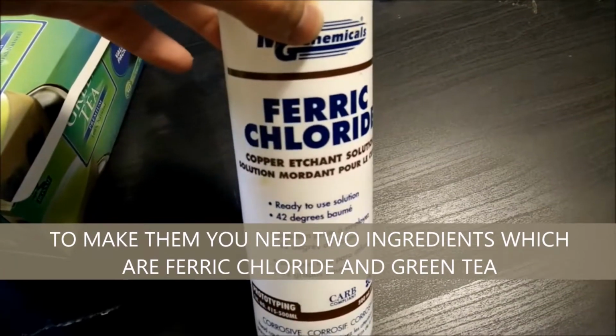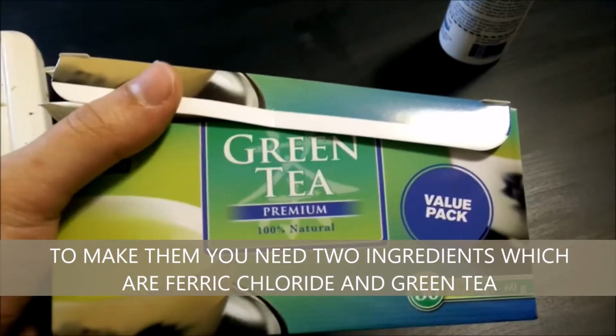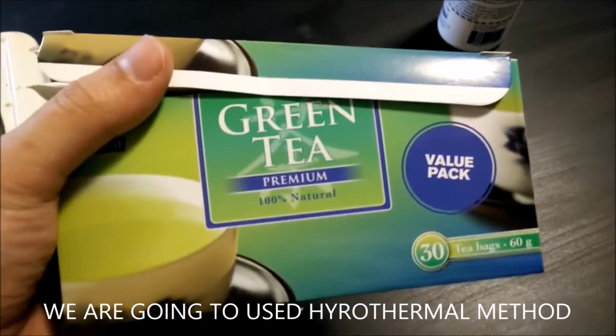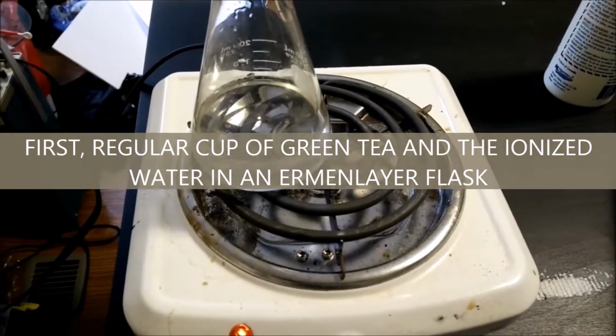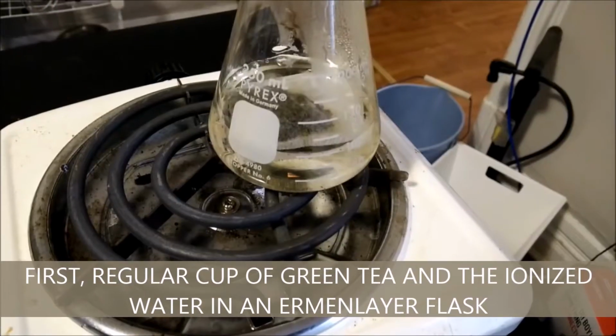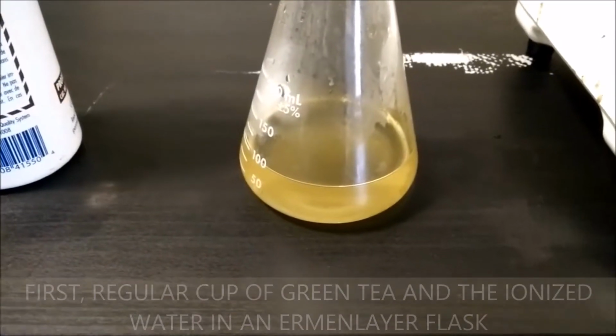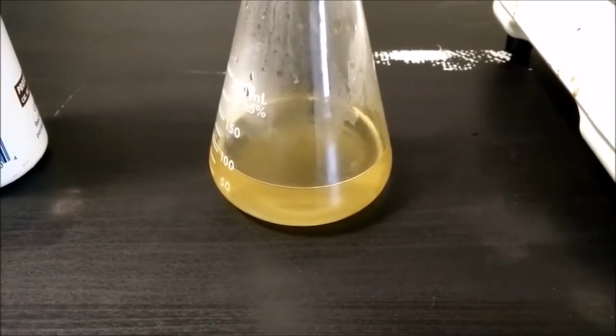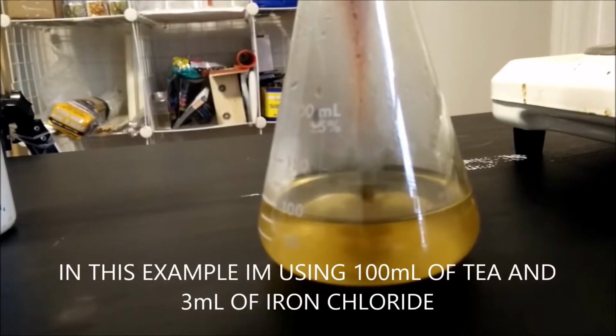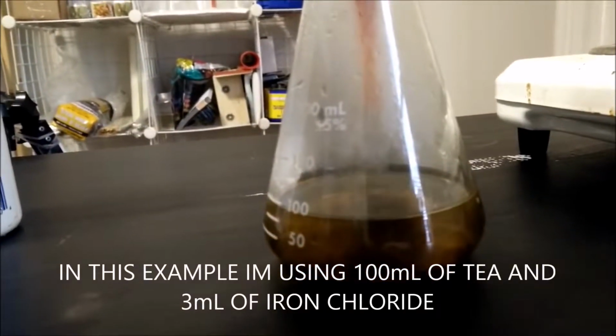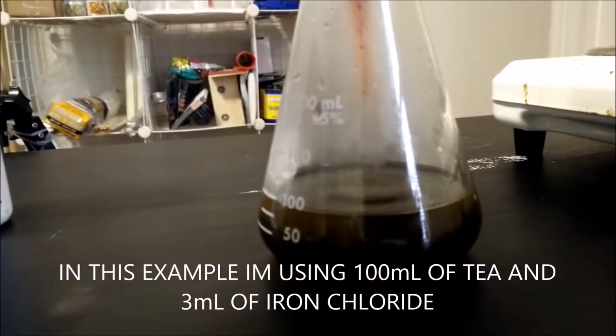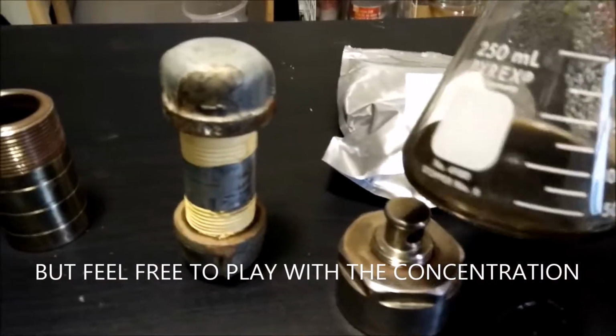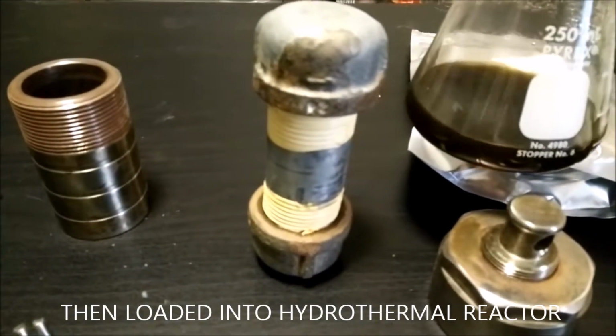To make them, you'll need two ingredients, ferric chloride and some green tea. We're going to be using a hydrothermal method. So to start, we're going to have to make just a regular cup of green tea. Here I'm using deionized water in an Erlenmeyer flask, but a jar and tap water will work fine. In this example, I'm using 100 ml of tea and 3 ml of iron chloride, but feel free to play with the concentrations. Then load it into a hydrothermal reactor.